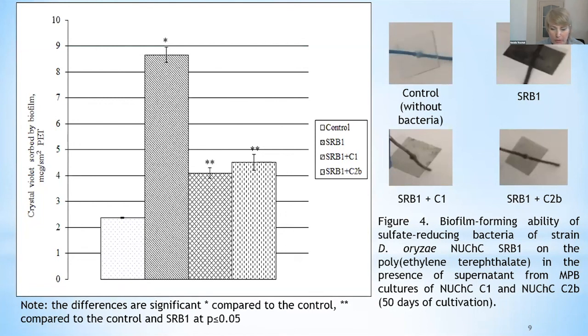It was found that the supernatant of the studied Bacillus velezensis strains significantly inhibits over time the formation of a biofilm on the surface of PET by the bacteria Desulfovibrio oryzae NUCC-SRB1. It should be noted that the inhibition of sulfate-reducing bacteria biofilm formation on PET by the supernatant of both strains was the same, despite the observed different level of expression of bacillibactin siderophore synthesis genes and the difference in the number of catechol type siderophores. Thus, the supernatant from meat-peptone broth cultures of Bacillus velezensis NUCC-C1 and NUCC-C2b inhibits the formation of sulfate-reducing bacteria biofilm on the polyethylene terephthalate surface.